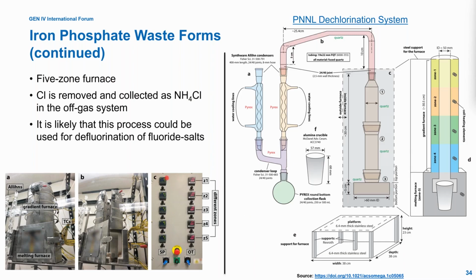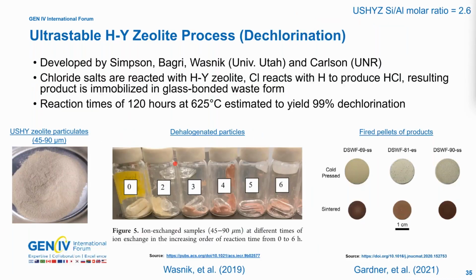It's got, as I said, 5 zones, but we also have over temperature controllers to make sure that everything is running as it's supposed to and we don't have anything heated to too high of temperatures. The ultrastable HY zeolite process I mentioned earlier is a way of dechlorinating salt using a hydrogen zeolite, where the hydrogen reacts with the chlorine in the salts and creates HCl, and then your dechlorinated product can be hot pressed into a monolithic waste form.